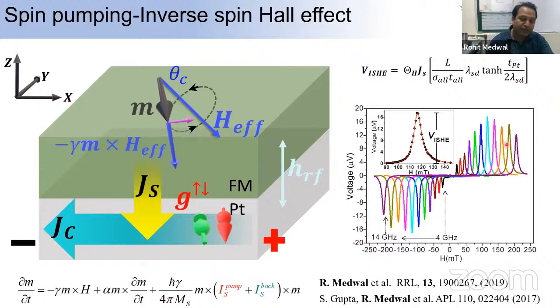And this inverse spin Hall effect voltage mainly depends on two contributions. Number one is the spin Hall angle, theta SH: what is the conversion efficiency of the spin which has been pumped from the ferromagnetic material to the platinum. Number two is the spin current: what is the amount of spin current being pumped from the ferromagnetic material to the platinum. These two factors are very important and contribute to the voltage we are measuring, which is V_ISHE, the inverse spin Hall effect voltage.